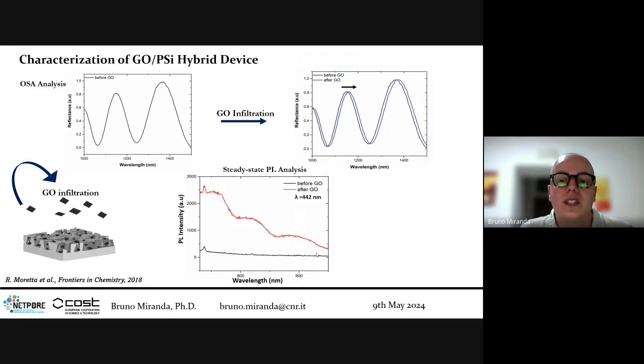We monitored each step, and here you have the graphene oxide infiltration. Before and after graphene oxide, you have a red shift in the reflectance spectrum, but also importantly, the macroporous silicon goes from non-photoluminescent to photoluminescent with a modulation. This modulation is due to interference with the reflectance spectrum, meaning the graphene oxide was directly inside the pore. Otherwise its photoluminescence would have been smooth, but instead you have these fringes due to the presence of the porous silicon.